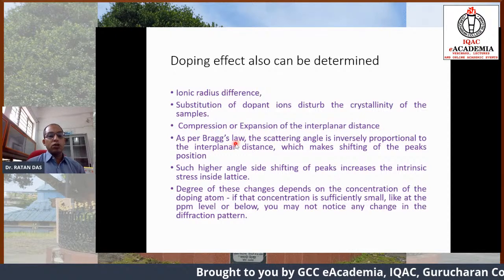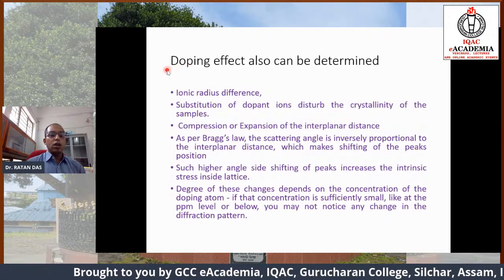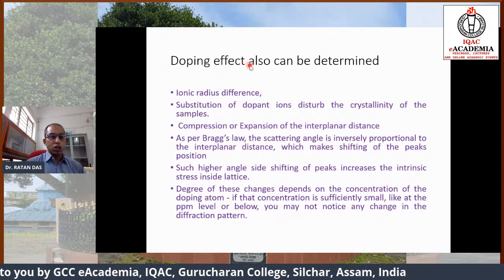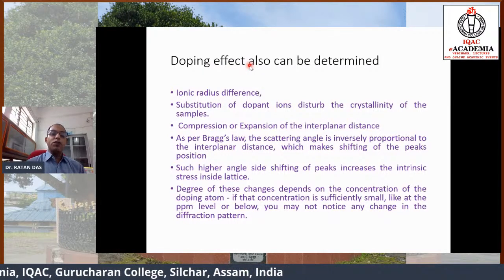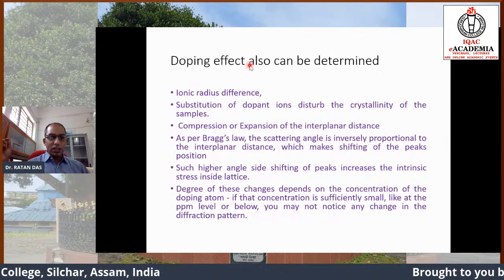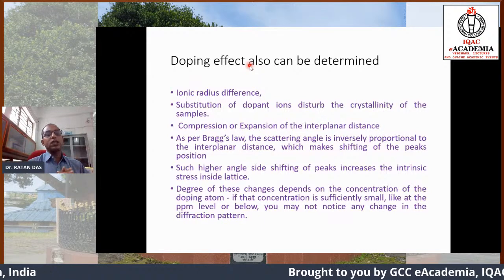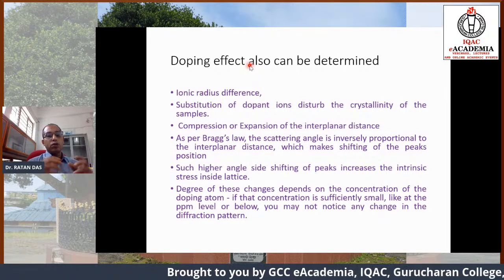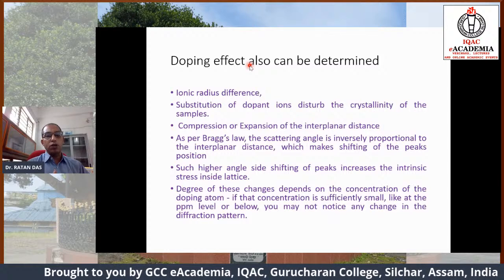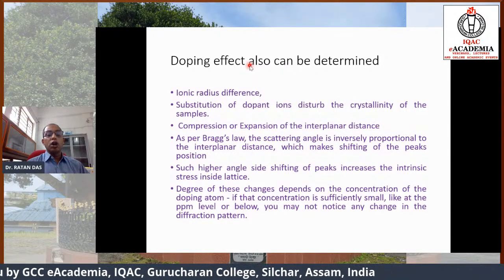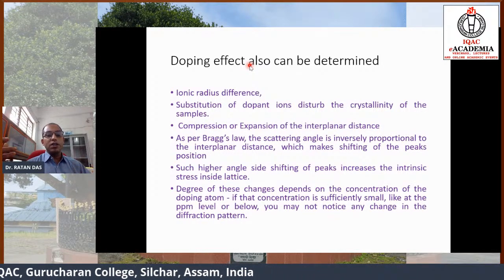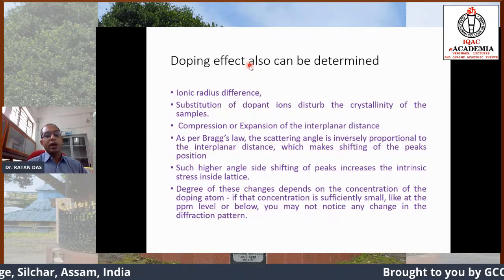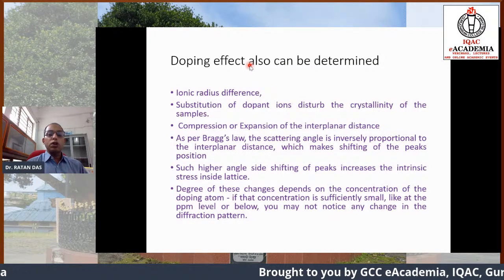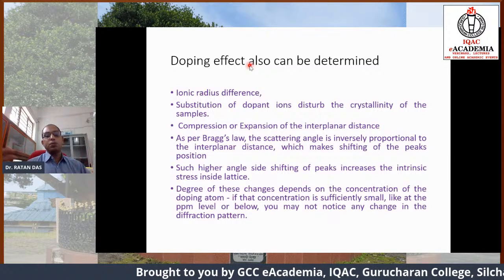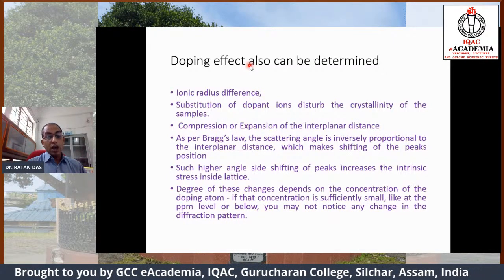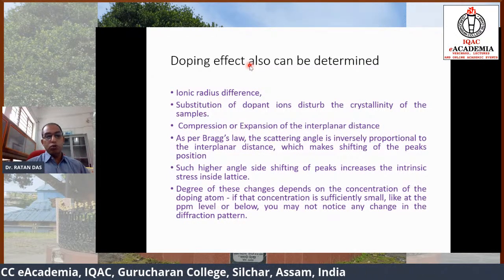Now a question may arise in your mind that this is a doping effect. But if we decrease the size without doping, if we decrease the size of a sample to the nanorange, suppose a 10 nanometer particle, then also some sort of disturbance in the crystallinity takes place because of the size confinement effect, and because of this either compression or expansion of the interplanar distance takes place, and thereby shifting of the peak position will take place.